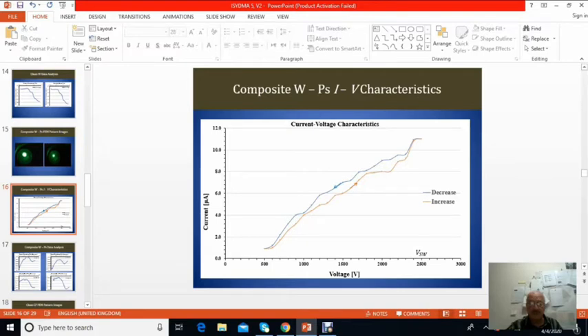So this is the V switch. It happened at 2500 volts and produced about 11 microamperes. So this is the increase. There is no saturation region, very little, not really worth mentioning. So this is the decrease, and then this is the increase. So it is almost the same, with a very small hysteresis effect.